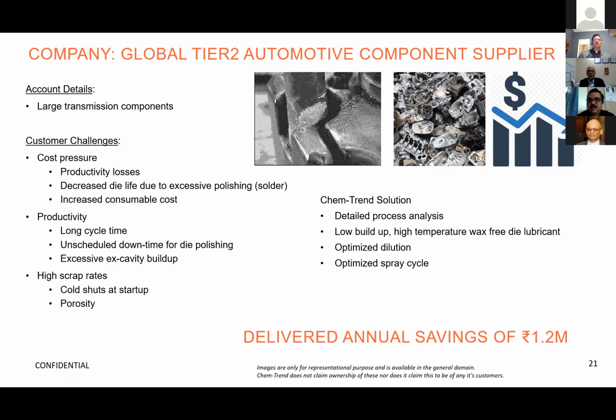We partnered with a global tier 2 automotive component supplier who was making large transmission castings. They had a lot of cost pressures, productivity issues due to frequent polishing, decreased die life due to excessive polishing, and erosion of the die surface. They also had increased consumable costs, which most of us ignore because we're ready to polish the die, but we don't add a cost to these consumables. With all this, the cycle time increased and the customer was not able to meet their schedules on time.